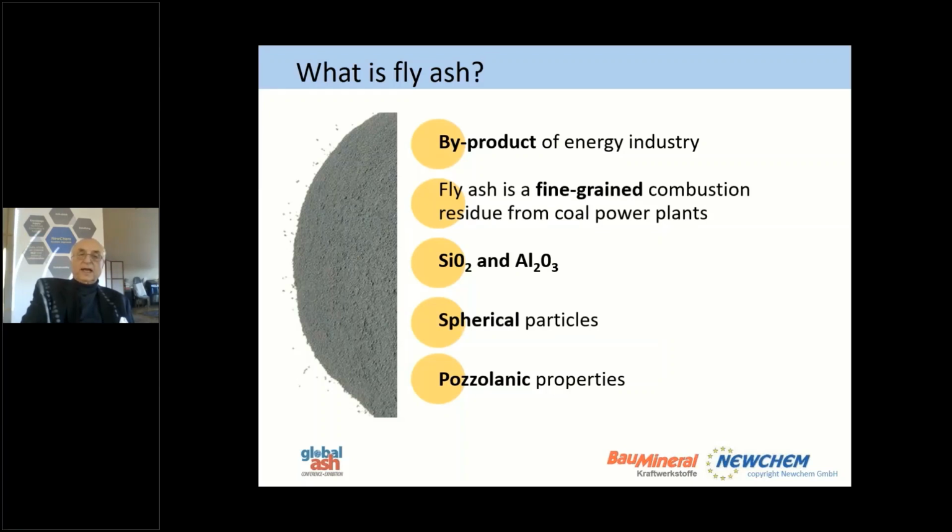in it. And this starts with the chemistry, because silicium with the calcium hydroxide or Portlandite of cement will give you calcium silicate hydrate, which is a cement binder. And the second cement binder will be the calcium aluminate hydrate. So these products are pozzolanic, therefore they are reacting with the free lime to give some binders.